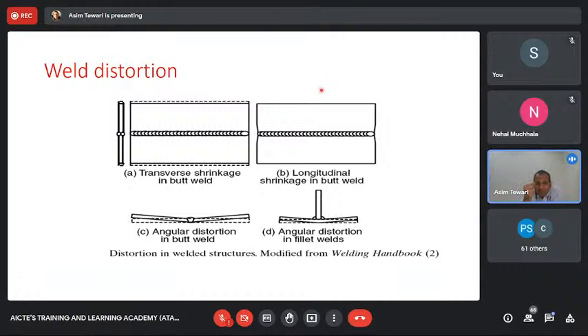to distortion in this. So if you look at this plate, what you'll realize is that the center has been welded, and it has been welded from the top. And since it has been welded from the top, once it cools down, it will create a tensile residual stress in the center. And the tensile is trying to pull everything down. And because of that, your actual plate, which was flat, will become distorted like this. You can think of the same for a T-joint, and a T-joint will also lead to that kind of distortion.